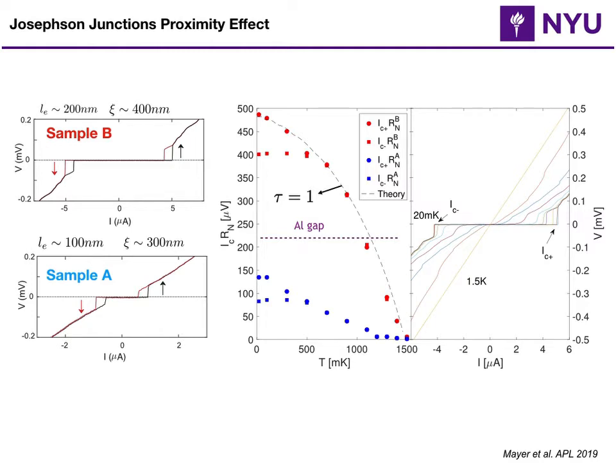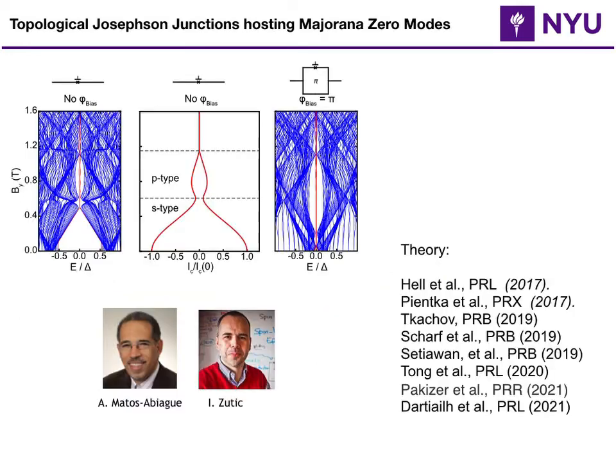And if you want to plot the ICRN as a function of temperature in terms of the transparency, we haven't tried to fit the data, but the dashed line is actually the perfect transparency. And you see the data fits quite well. But we picked these best junctions, it's basically sample B.